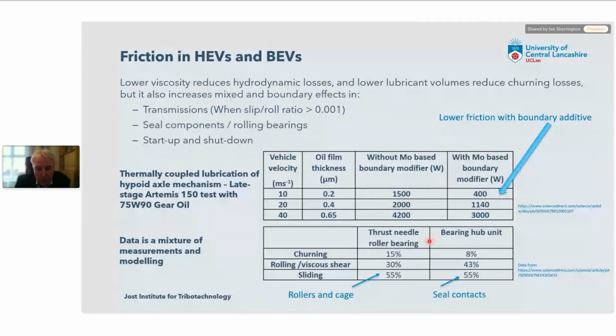Similarly, if we look at other components, so a needle roller bearing here and a bearing hub unit, you can't see this number on here, but it's 55%. These proportions here are a significant proportion of the losses in these particular types of component. And so if we don't model these, we miss quite a lot of the friction contribution that we should be seeing in our models.